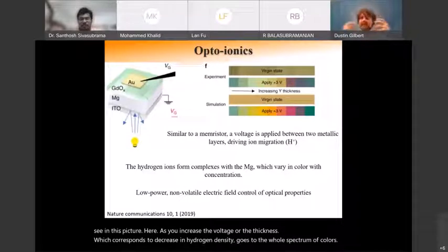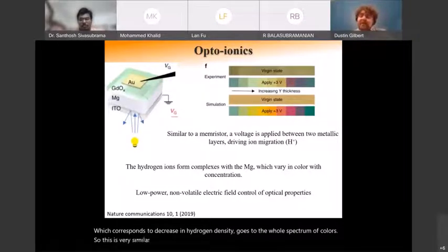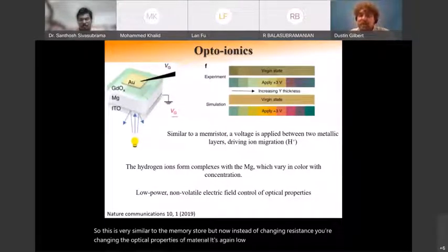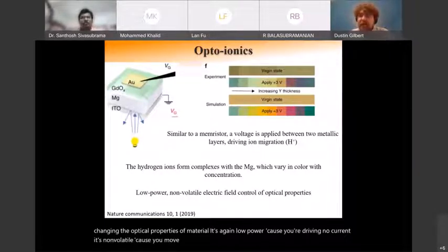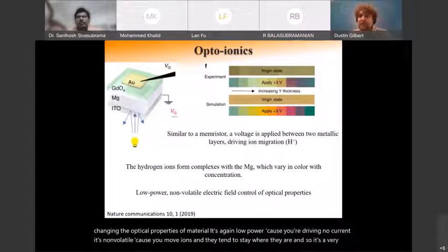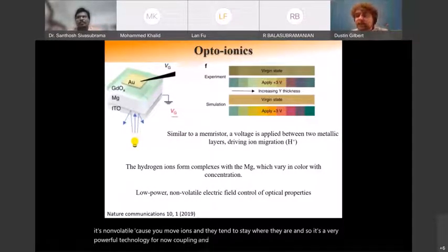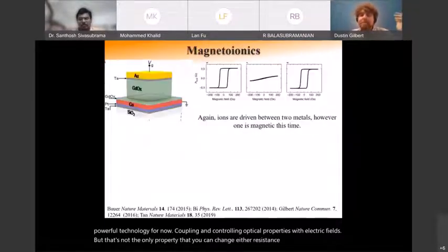So this is very similar to the memristor, but now instead of changing resistance, you're changing the optical properties of the material. It's again low power because you're driving no current. It's non-volatile because you move ions and they tend to stay where they are. And so it's a very powerful technology for now coupling and controlling optical properties with electric fields. But that's not the only property that you can change either. Resistance, optical. How about magnetic?